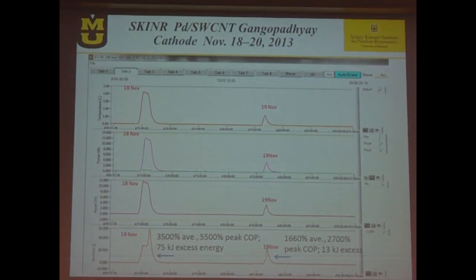Now, this is one of the experiments that we just got lately with carbon nanotubes, and basically we are talking about palladium overplated with palladium as an adhesion layer, and then the carbon nanotubes and another layer of palladium or rhenium or lanthanum or all kinds of those materials that you saw in the statistics slide.